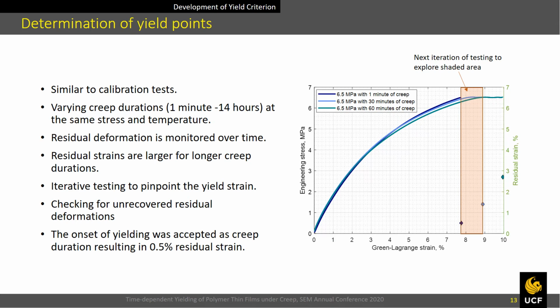For the determination of yield points, the following procedure is adopted. For a fixed temperature and creep stress level, several experiments are carried out with varying creep durations. To illustrate, the figure shows graphs of 3 different tests conducted at 6.5 MPa at room temperature. Corresponding residual strains are also noted in the graph. It is clear that as the creep duration increases, the residual strains increase.